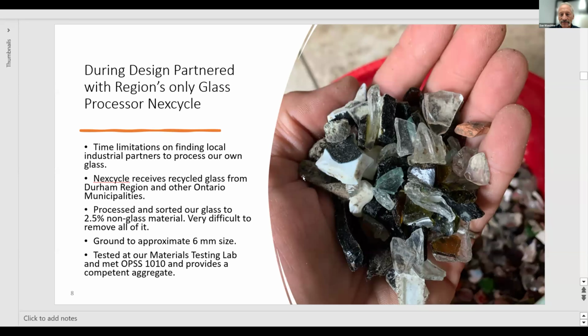We took this sample and blended it with some of our typical granular A and B, tested it at our materials testing lab, and it met the requirements of OPSS 1010 and was found to provide a competent aggregate.